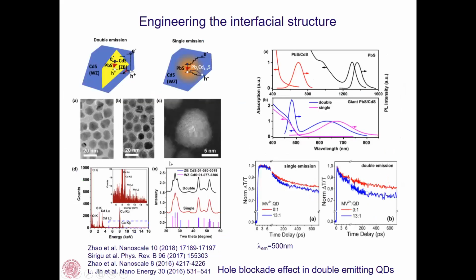Our hypothesis is that we can have double emission when we have a very neat interface between the core and the shell. What if we are able to produce a graded interface? In this case, we are removing the effect of the hole blockade, and we should obtain a single emission in the close to infrared region. And this is what we obtained here.